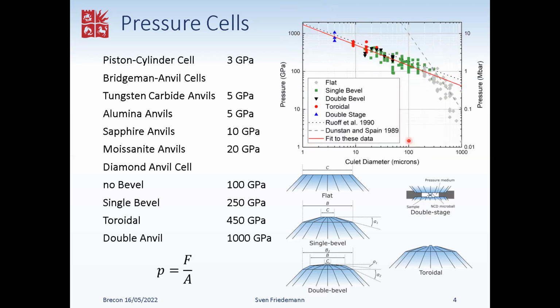Right. So yeah, this curve shows the record pressures that have been achieved as a function of the culet diameter. So that's the diameter of this flat bit at the front, which of course does set the sample space and hence the sample size. And you can see that without a bevel, one can get to about 100 GPa, and beyond that one needs a double bevel, and the slope goes down a bit.